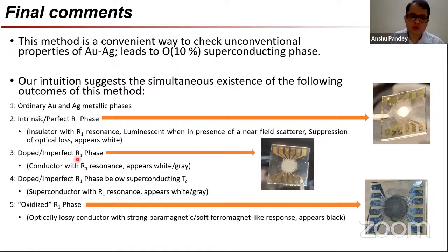This sort of film ends up being an insulator. If we have some form of a doping or an imperfection in the R1 phase, which essentially means an overstoichiometry of gold in simple terms, that gives rise to a conductor which does still have the R1 resonance, but has a more grayer appearance than the usual film, and it is somewhat more optically lossy. That's the only difference between these two. This, when cooled below its TC, would give rise to superconductivity-like observations, where it apparently starts having vanishing resistance.